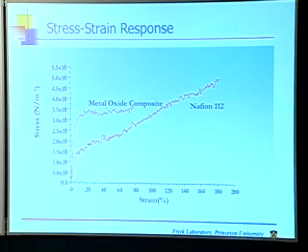I do the same thing with 3% titanium in there. And first of all, you'll notice my elastic region is about twice as large as before. And now I don't deform. I just stagnate when I get in this region. So in other words, I've changed the mechanical properties of the Nafion. When I have the metal oxide there, I don't have to be concerned about an irreversible deformation that destroys the structure that I have there.